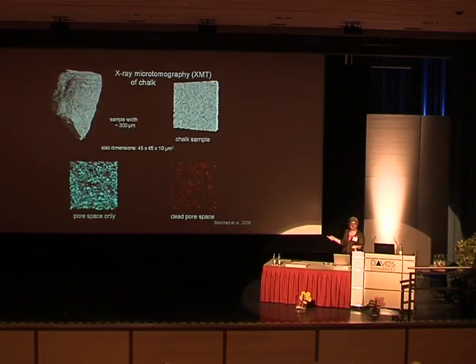So here we have a sample of chalk that has been electronically cut out of our sample. Oh, I should say that the pixel size, pixel is a two-dimensional measure. A voxel is a volume pixel, so it's 3 dimensions. And these volume pixels in our tomography setup at the moment have about 350 nanometers of space.